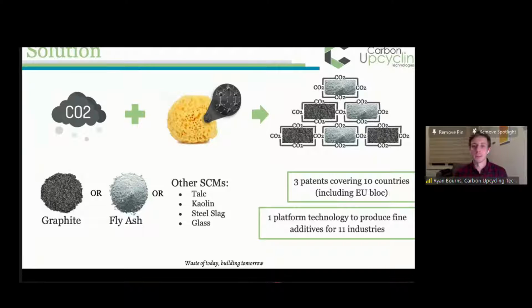And so we've done this with a patented carbon utilization process where we take gaseous CO2 emissions and chemically absorb that CO2 into inorganic raw feedstocks. So these could be materials like I've described here, either fly ash or talc, or other industrial waste like steel slag or crushed glass. So we use that material, like that fly ash, to act like a sponge where it's soaking up CO2. But at the same time, we are exfoliating the surface of it, which starts to resemble something like that sponge there, where there's more surface area and more pores within the fly ash.